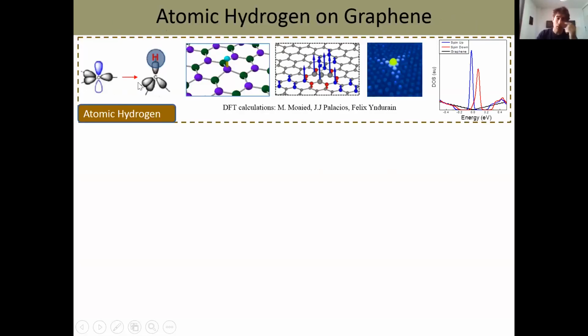So how does hydrogen adsorption take place? Well, we have here graphene with the sp2 hybridization. When you adsorb a hydrogen atom, it binds on top of a carbon atom, and then the hybridization of graphene changes from sp2 to sp3. So here we have the atomic structure. This is the hydrogen atom. It binds with the carbon atom on top of it, and then it forms a covalent bond with it. So in this covalent bond, you need two electrons. One of them comes from the hydrogen itself, and the other electron you are borrowing from the graphene pi network. So this is a very efficient way of removing the blue orbital that we wanted to remove. So once we remove this pi electron, immediately a magnetic moment emerges around the adsorption of the hydrogen atom.